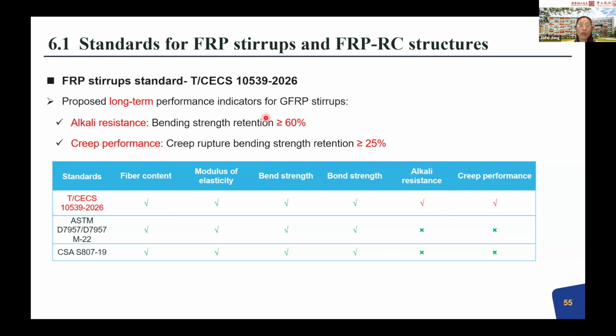Here we introduce the limits for the alkali resistance reduction and for the creep performance. Here is following the 90 days under the standard test method for FRP longitudinal bar. And for creep performance, also under the standard creep testing for FRP longitudinal bar. So these are the two limit ratios we have regulated in this code.